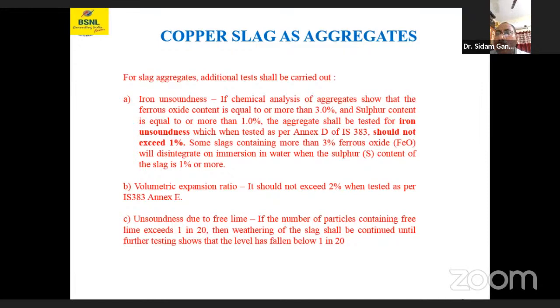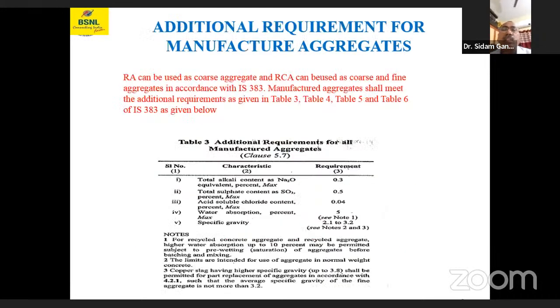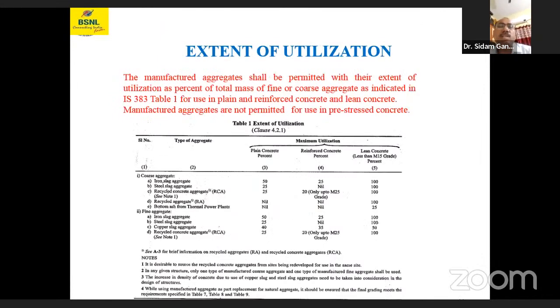Next, soundness due to free lime. If the number of particles containing free lime exceeds 1 in 20, then weathering of the slag shall be continued till further testing shows that the level has fallen below 1 in 20. Next, additional requirements. Next slide, please.